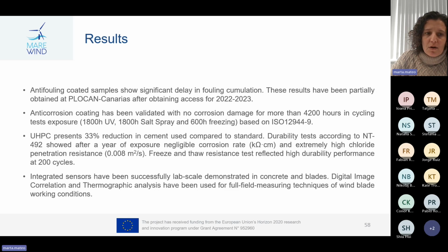Ultra high performance concrete presents 33% reduction in cement use compared to the standard. Durability tests according to the standard show after 1 year of exposure negligible corrosion rate and extremely high chloride penetration resistance, which is important in this case, and also the freeze and thaw resistance test reflected high durability performance at 200 cycles.